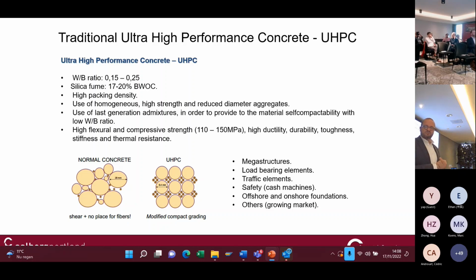So first, to talk about UHPC, we start with traditional UHPC, because after that I would like to take the step to the new generation of UHPC, but first the traditional UHPC until today. The important parameters are the water-binder ratio, very low, of course, between 0.15 and 0.25. Here we are also talking about a high amount of silica fume, 20% by the weight of cement. These kinds of mixes are also characterized by a high packing density. This is important to achieve the high compressive strengths between 110 and 150 MPa, even higher. And also the high ductility and the durability are important.